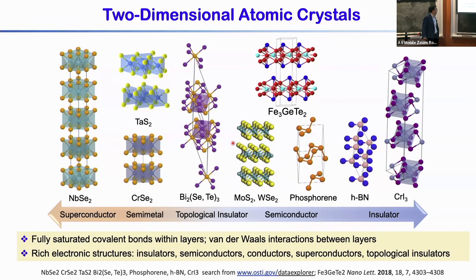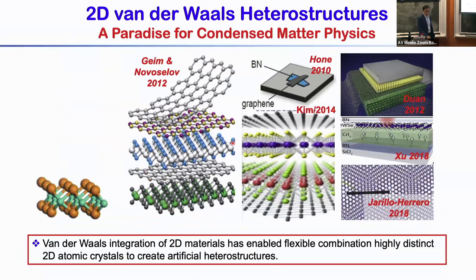With 2D layered materials, they have covalent-bonded atomic layers held together through van der Waals interactions. These van der Waals bonded atomic layers can be separated into individual layers to form single or few-atom layers. With these single few-atom layers, unlike traditional 3D materials, they have fully saturated surfaces. A fully saturated surface means they can largely maintain their electronic properties even as a single or few atomic layers. This actually opens a lot of opportunity, particularly in trying to combine different atomic layers — we can exfoliate them into individual layers and restack them.